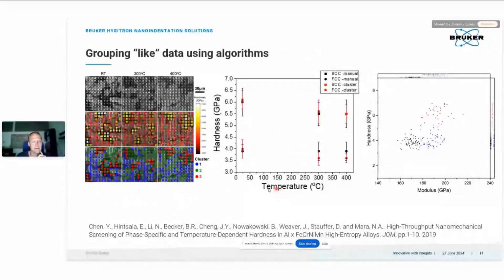In this case, I'm presenting clusters measured at different temperatures. So you can also break the microstructure into different clusters and study how the material properties are changing with the temperature for different structural organization or crystallographic orientation. This is, I would say, quite a popular approach nowadays. And since the measurement is very fast, you can also beneficially do it at high temperature, so you don't consume your tip too fast when you're using this fast indentation approach.